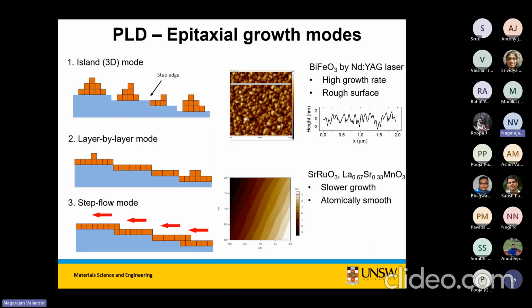We put strontium ruthenate, LSMO over here. But we can get that kind of growth with bismuth ferrite on a layer in one of our chambers. The one that has the large distance, that growth is so slow that we end up getting bismuth ferrite with almost 10 days. And that becomes quite important when you're doing superlattices, because in that case you only have a few nanometers, and you can't have these rough height profiles disturbing the electrostatic boundary.